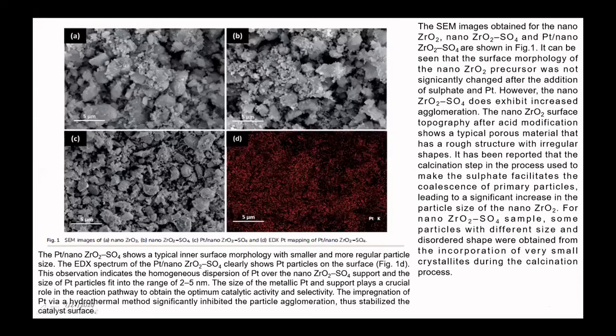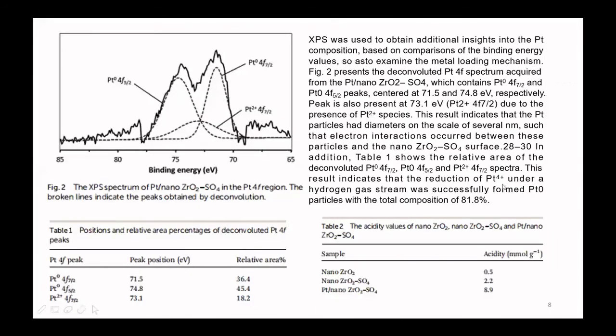Using XPS, we can also observe that the conversion is good. With oxidation followed by reduction using hydrogen gas, we obtain more than 80% of the platinum in the form of platinum zero. So the rest is maybe still in salt or oxide form, mostly maybe still in oxide form.